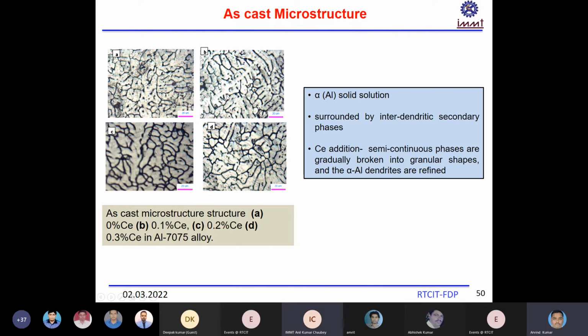So here you can see the microstructure, where we are increasing cerium from 0.1 to 0.3%. This is 0, 0.1, 0.2, 0.3%, and actually the alpha matrix was surrounded by the intermetallic secondary phases. With this cerium addition, you can see these continuous phases are broken, and a granular type of alpha dendrites are forming.